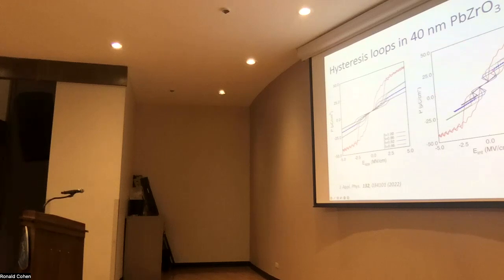So what happens if the surface charge compensation is very good, then the negative slope does not appear. But as we begin to compensate less and less, we can see emergence of the negative slope. So this computational data demonstrate that in order to reach that negative capacitance regime, we really have to introduce the depolarizing field, and we have to look into the response to the internal rather than applied electric field.